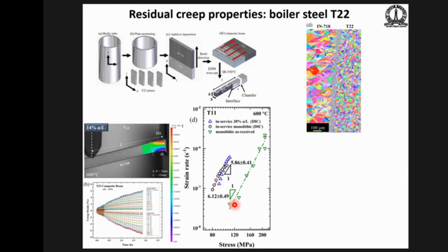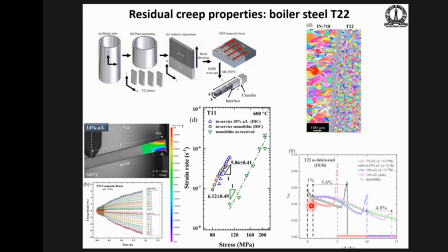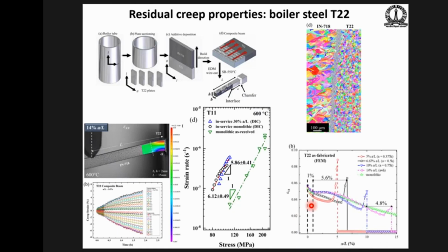Now, of course, the interesting point here is how much smaller can you make it? So here the cantilever was, let's say, L. We were working with a sample just 0.3 L. It turns out that you can get to about the beam thickness. That is, you can use practically a stubby coupon where the thickness is the same as the length, and then just add on a long handle of something else. So this is a way of greatly reducing the amount of material that needs to be extracted, which is obviously useful if the component has to continue to be in service while you're doing all these analyses.